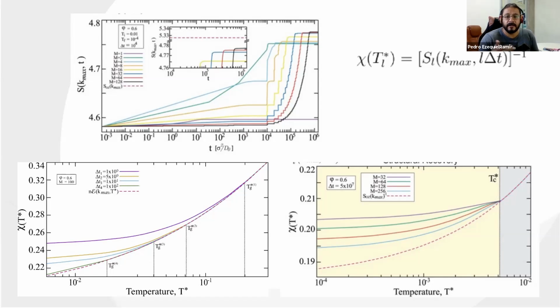Now, we can present the information in a different way. If we define chi of t as a response function associated with the inverse of the time-dependent structure factor, we can obtain the two plots at the bottom of the screen. In both, the dotted line is the equilibrium value of chi of t. The left plot presents results for fast cooling rates, and we observe that the deviation from equilibrium starts to appear above Tc. In contrast, at the right, we found that for slow cooling rates, the temperature where the departure from equilibrium begins is observed at Tc. In consequence, Tc separates the states which actually equilibrate from the ones which are not able to equilibrate.